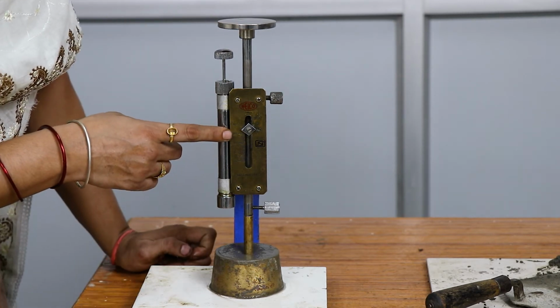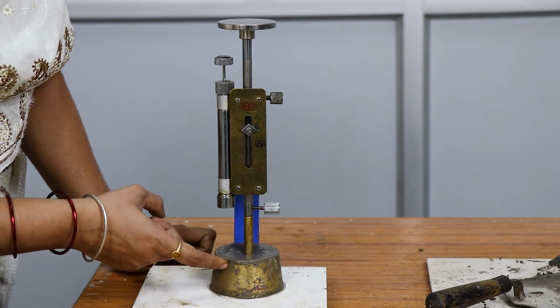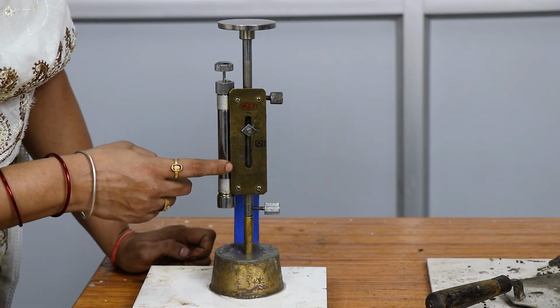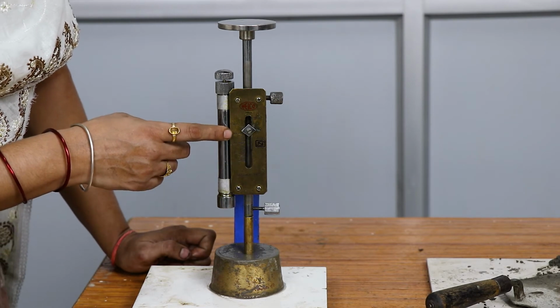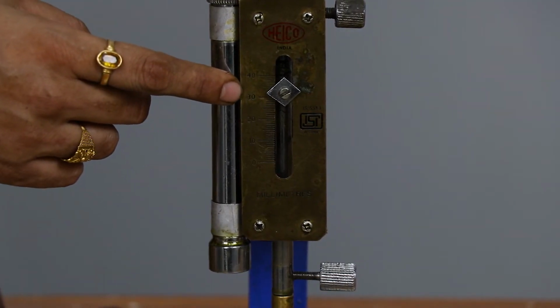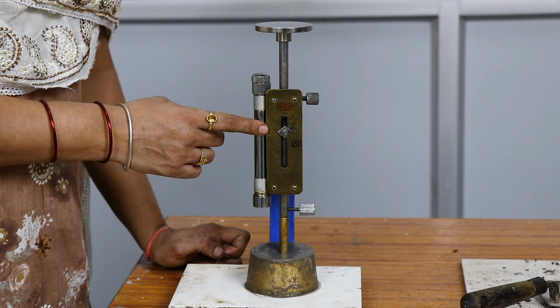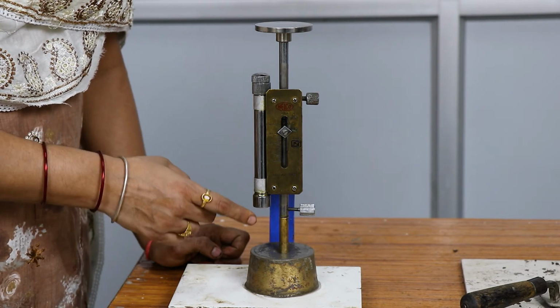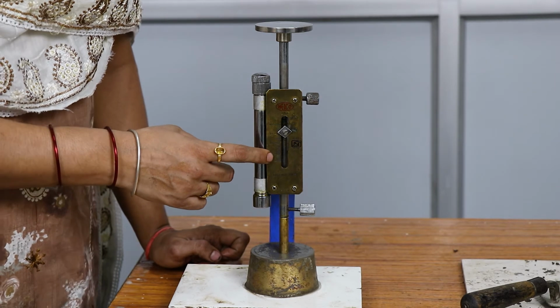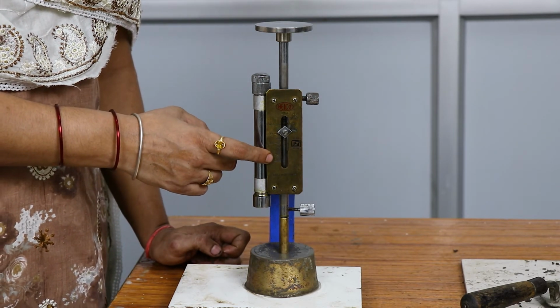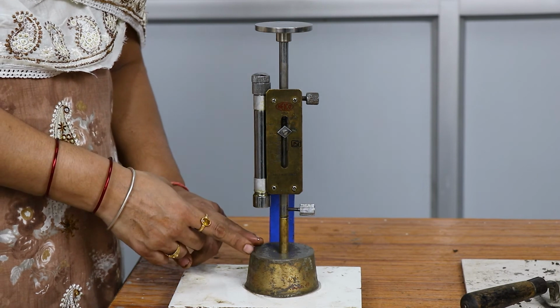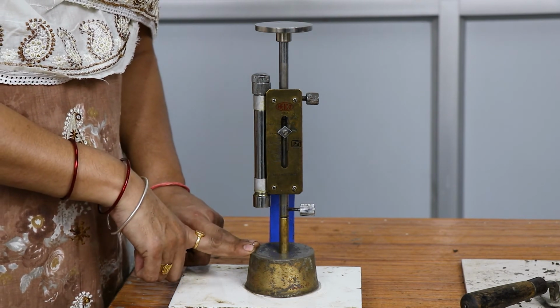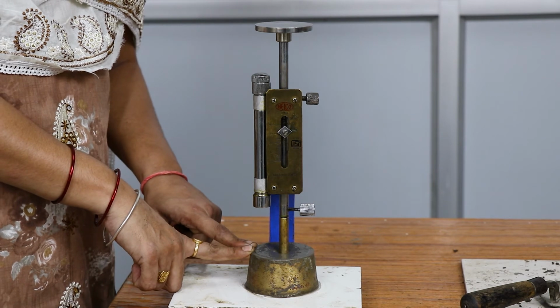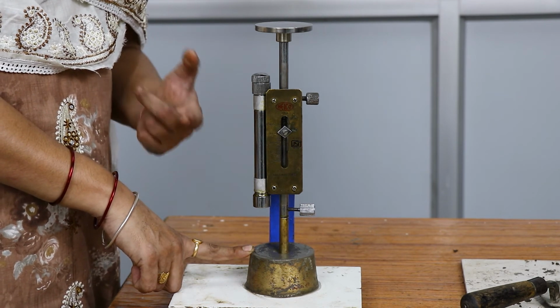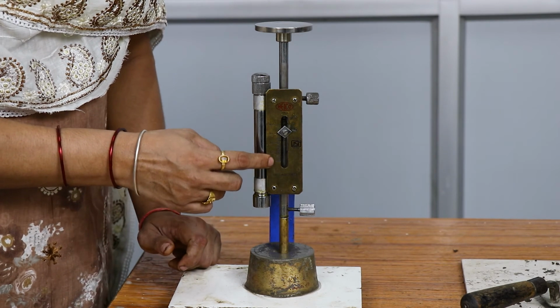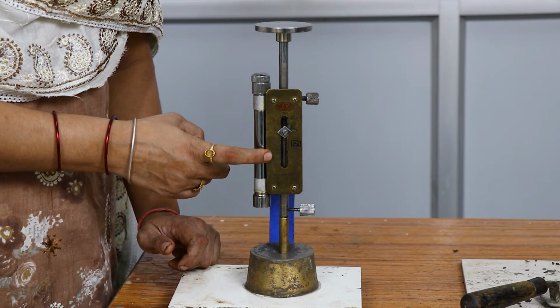So the reading comes out to be, from bottom, how much is the penetration of the plunger? The penetration of the plunger from bottom is 30 mm. The standard consistency is the consistency when the Vicat plunger penetrates 5 to 7 mm from the bottom. That indicates that the 28% water which we have taken to prepare the cement paste is not sufficient. So we will change the percentage of water and vary it to 30-31 so that we get a penetration of the plunger of 5 to 7 mm.